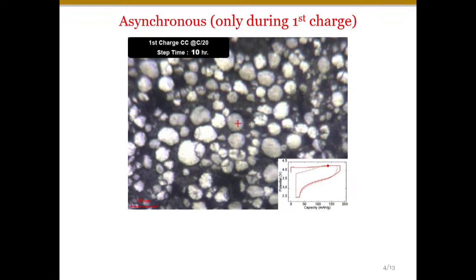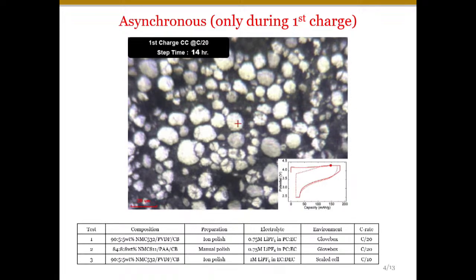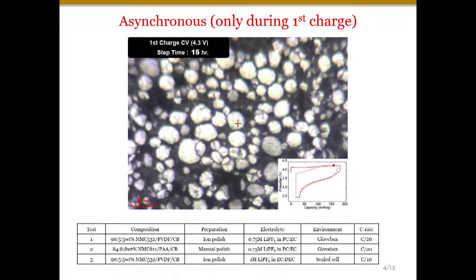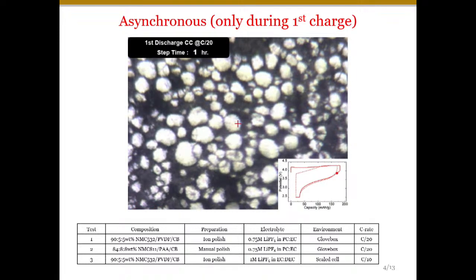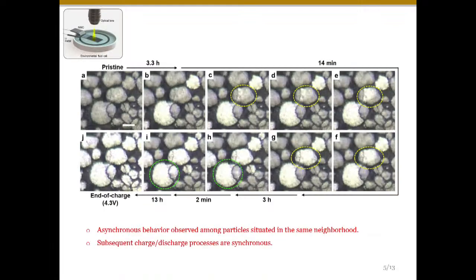This effect occurs only during the first charge, and we did not observe it during the later first discharge, second charge, third discharge, and so on. To confirm the repeatability, we tried with different transition metal ratios, different electrolytes, and we used a very slow C rate, like C by 20, taking around 20 hours to charge the battery.